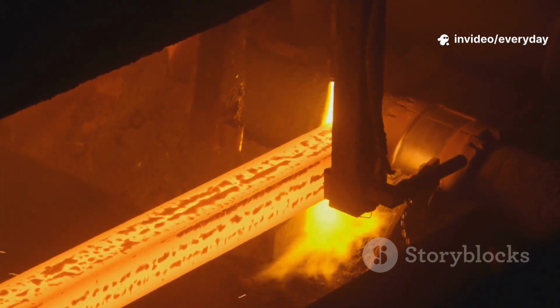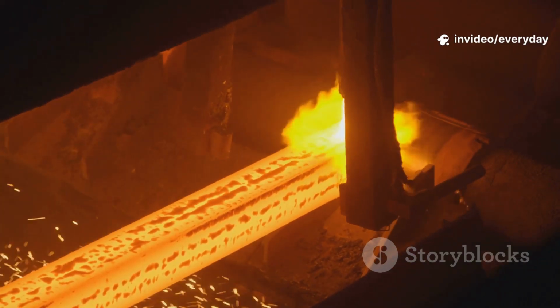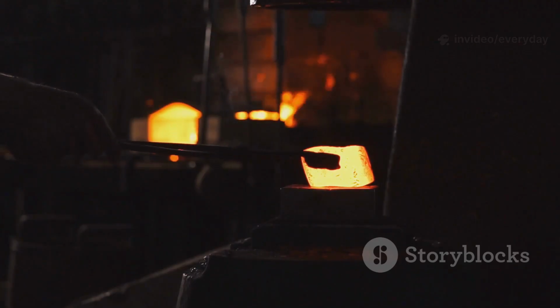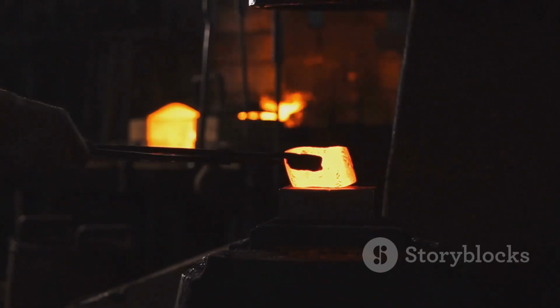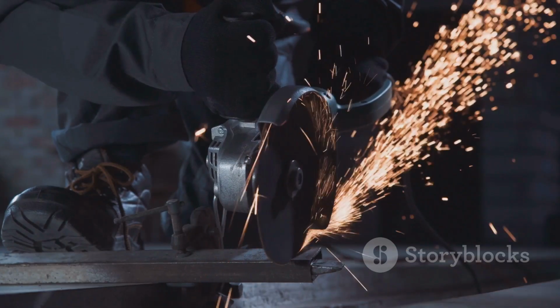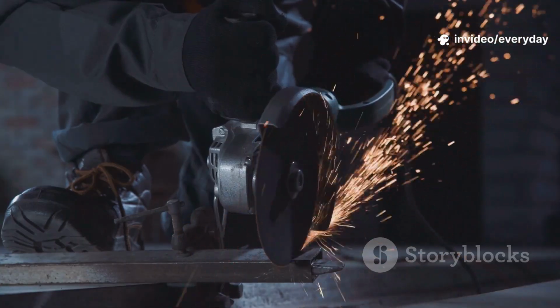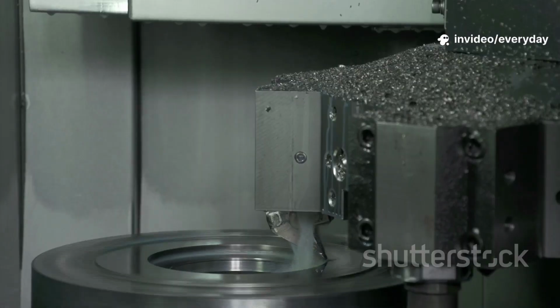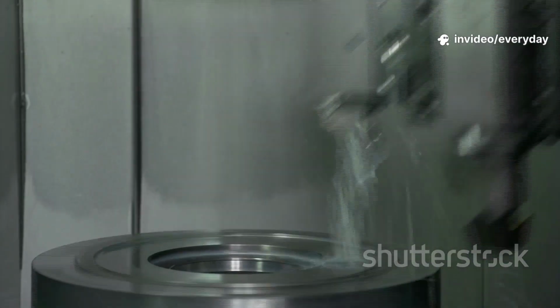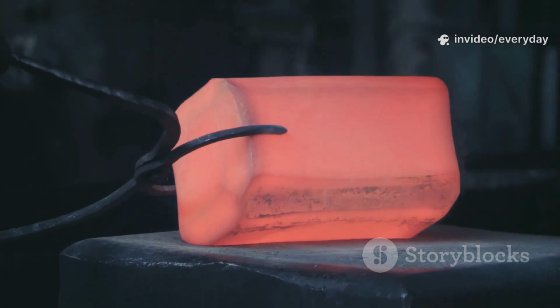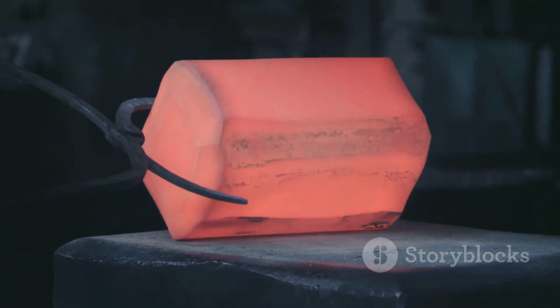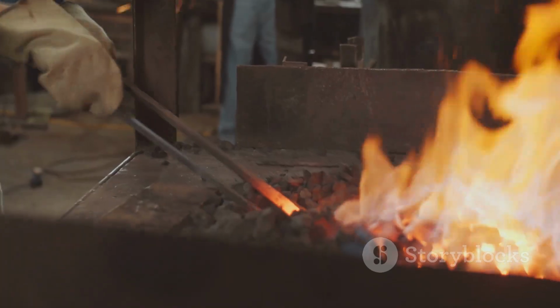Strong welds start long before the fire, with meticulous prep. Any contamination creates barriers and inclusions that cause delamination. Use an angle or belt grinder to reach bright, raw steel. Pay special attention to edges and corners. Seal the whole seam. Don't touch clean surfaces. Skin oils can ruin a weld. Handle by unground sides or wear clean gloves.